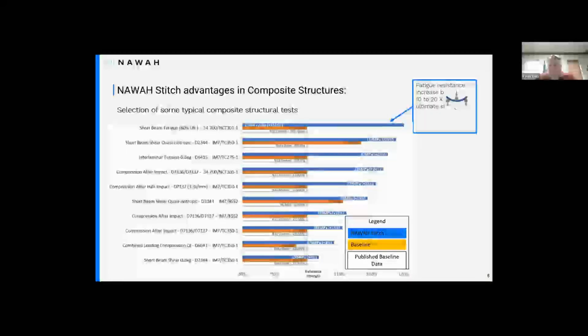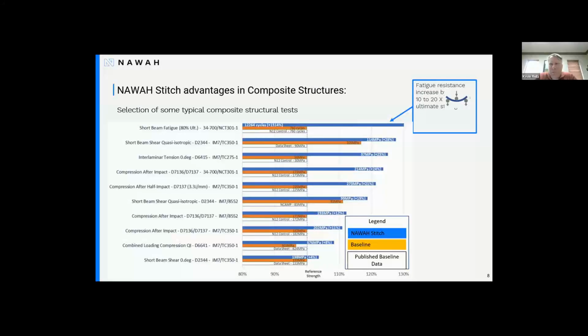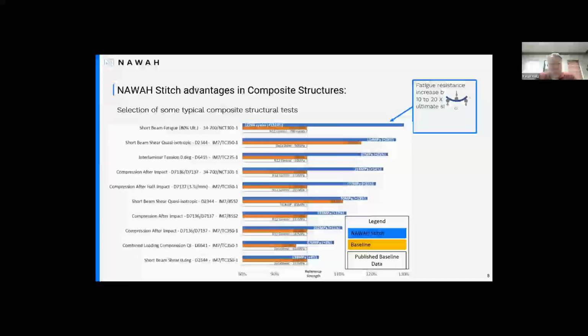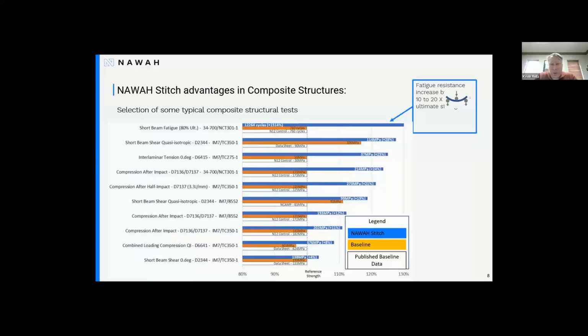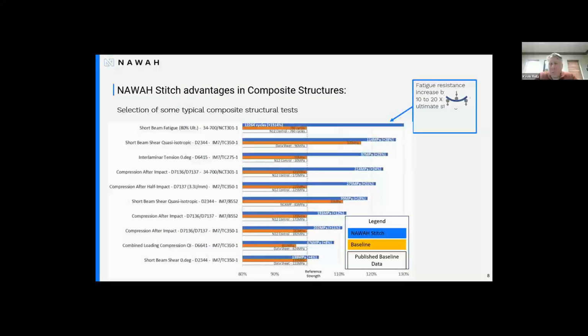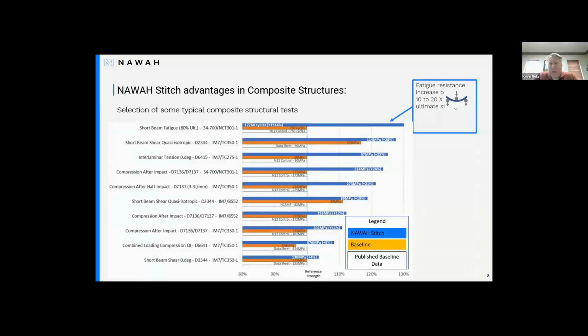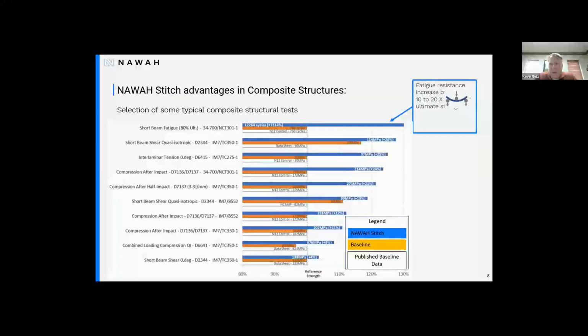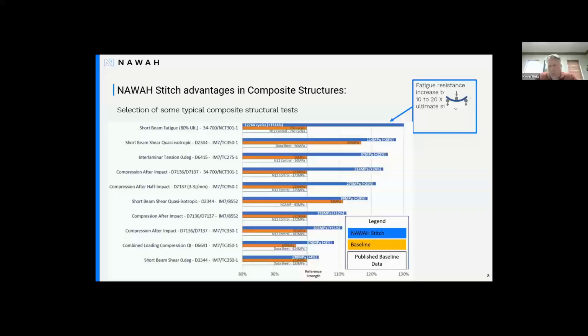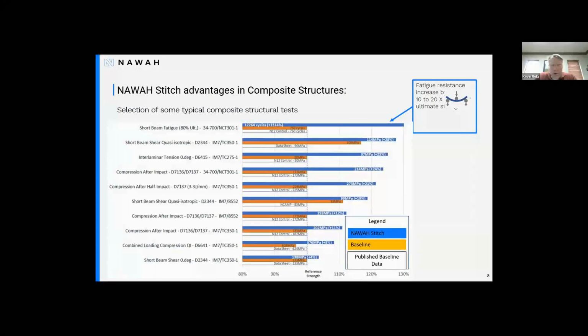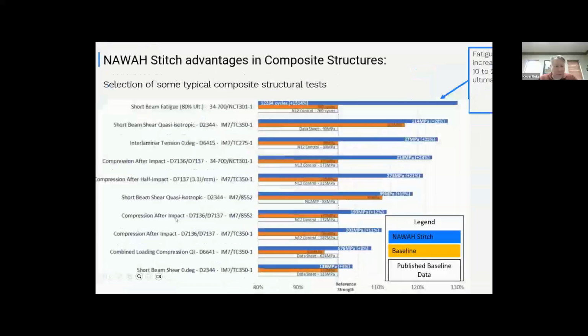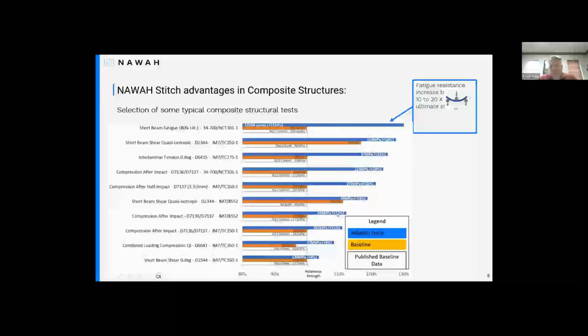What that does: if it is a resin-dominated property, that's where the vertically aligned carbon nanotubes work. If it is a fiber-dominated property, no. So we're not changing the dynamic of the fiber itself. We're changing the dynamic of the system, predominantly the resin area. So as you can see at the very bottom, short beam shear on a 0-degree panel, we're not getting a lot of improvement because there it's mostly fiber dominated. But when you get into compression after impact, then you're getting 12% or plus.